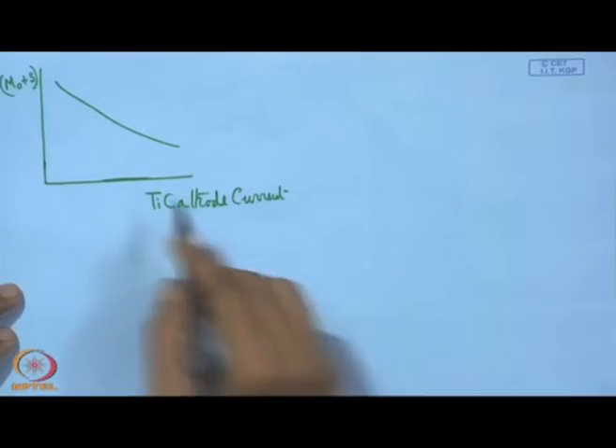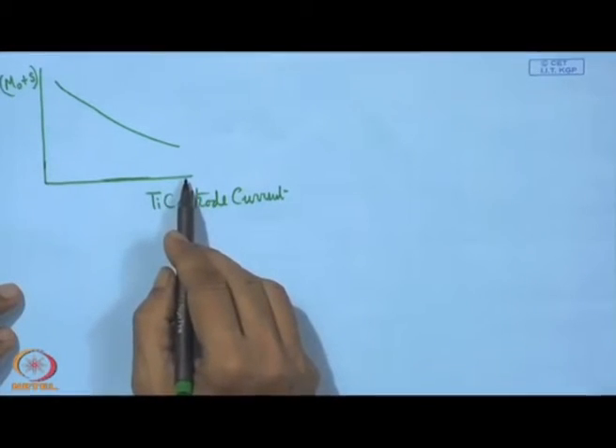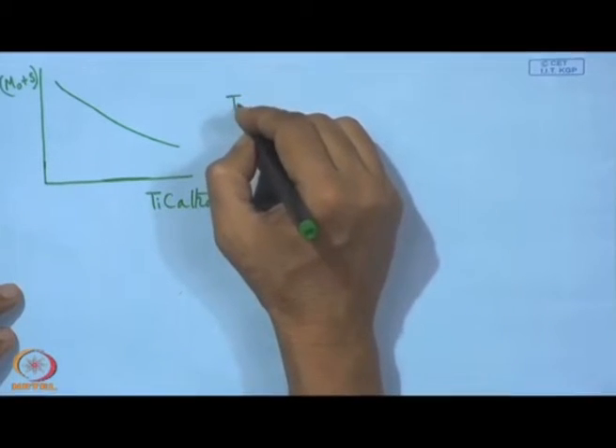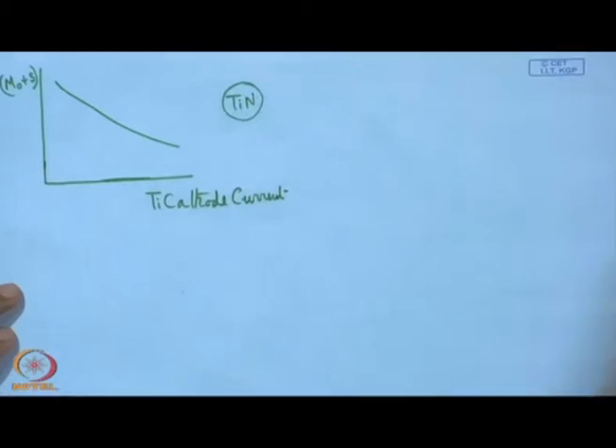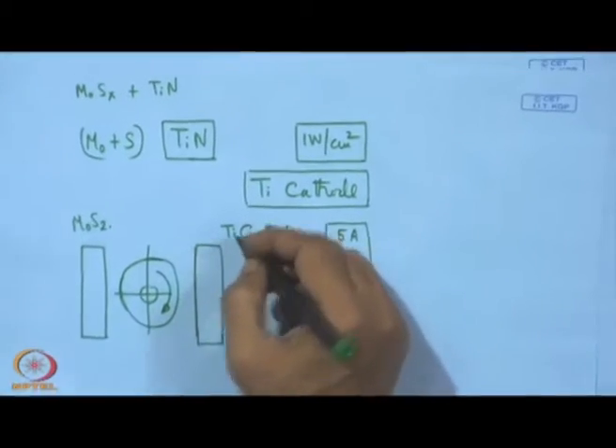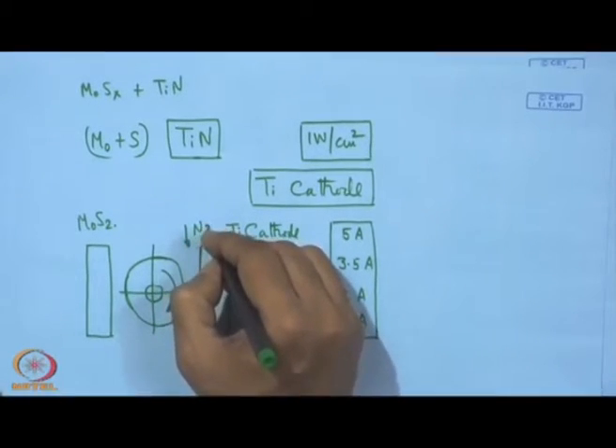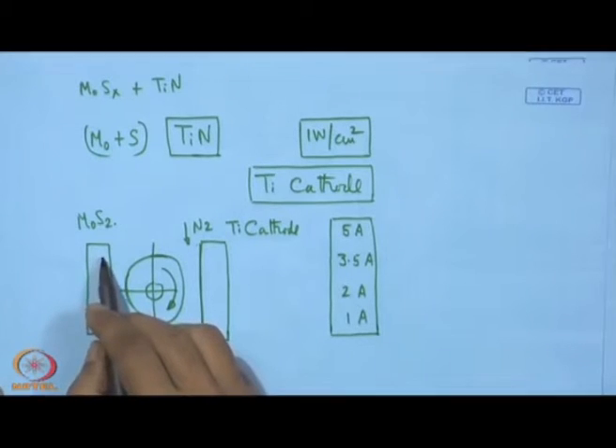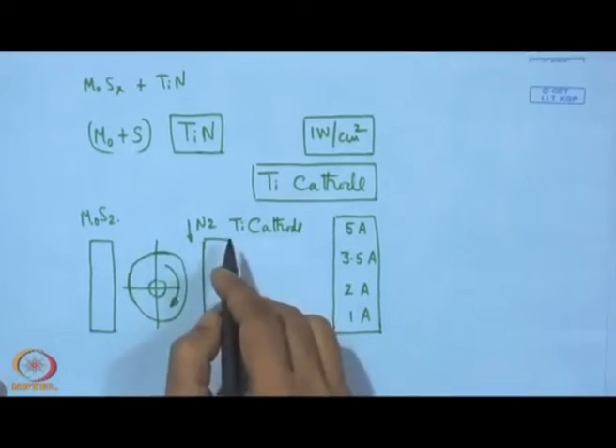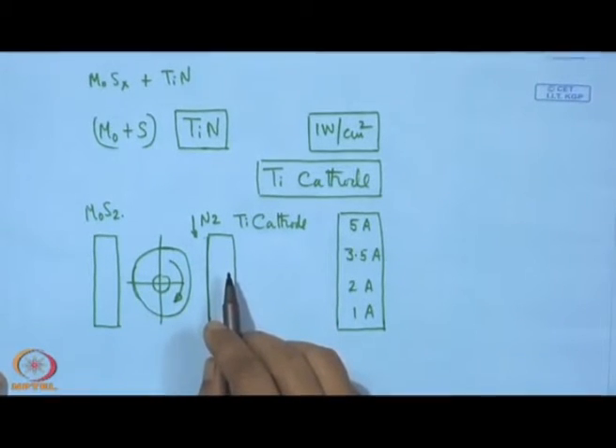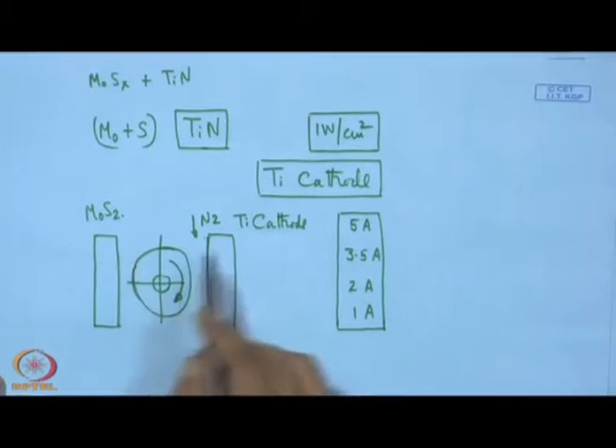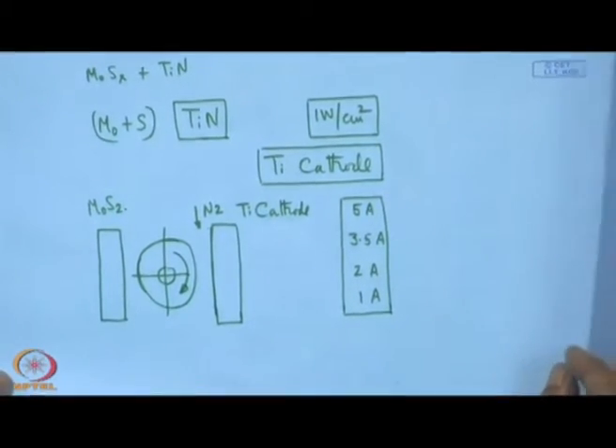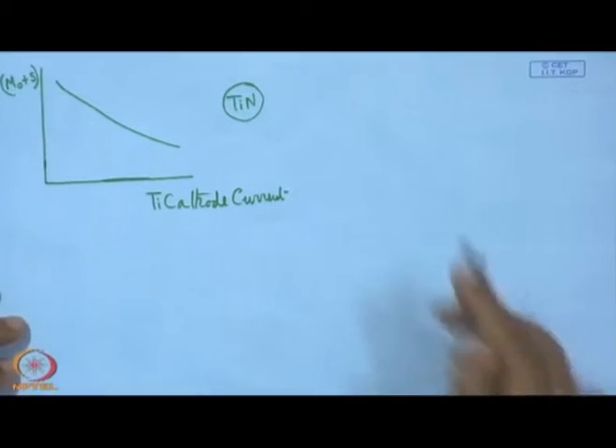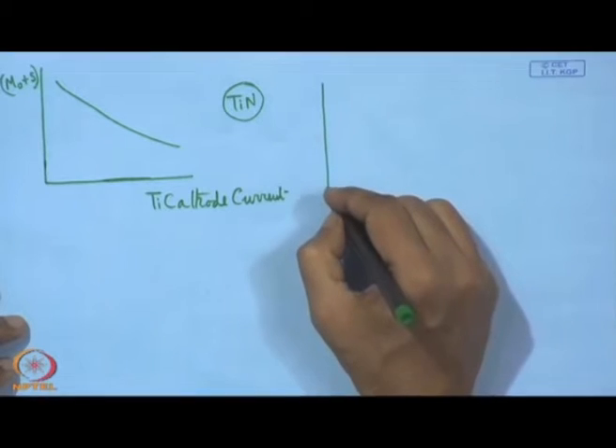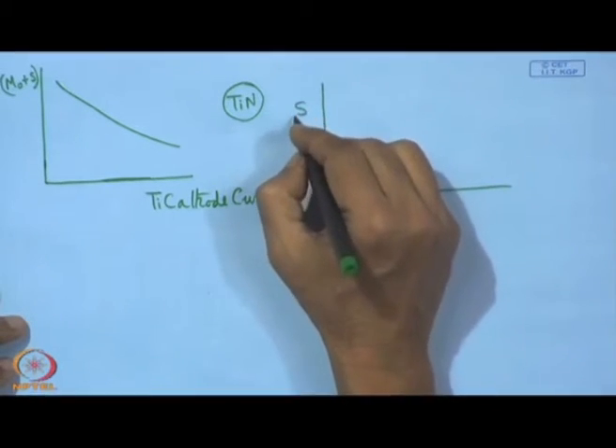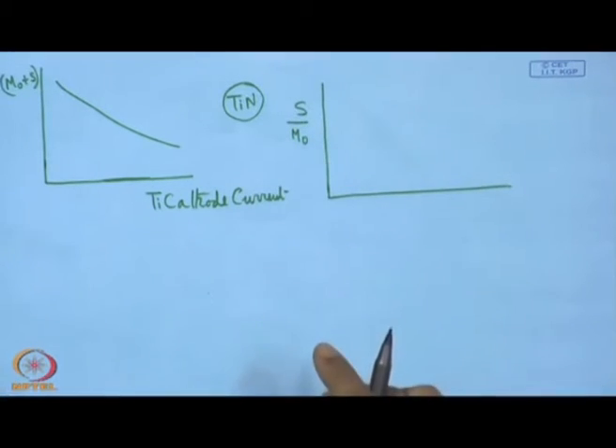So, percentage of Mo and S. When we have a higher value of titanium, naturally we have a higher percentage of titanium nitride in the coating. So, this is actually a reactive sputtering, where titanium and nitrogen admission gives titanium nitride, and then MoS2 as a whole is deposited. So, it is a reactive sputtering of titanium nitride and direct sputtering of MoS2 using a pulse DC system. And we have another observation in this case, that is the S by Mo ratio.